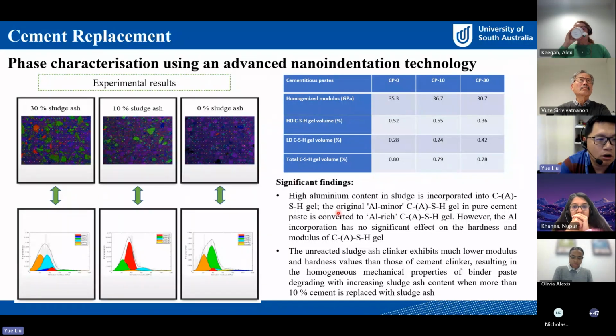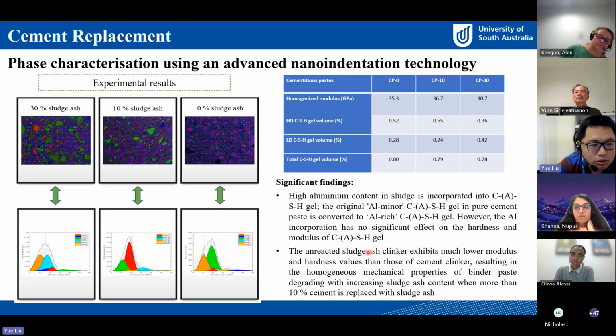We found that the original C-S-H gel in pure cement paste is converted to aluminum-rich C-S-H gel, and the aluminum incorporation has no significant effect on the hardness and modulus of C-S-H gel. Also, we found the unreacted sludge shows much lower modulus and hardness values than the unreacted cement clinker. For sludge, the modulus value is around 40 gigapascals, but for unreacted cement clinker, it's around 100 gigapascals.